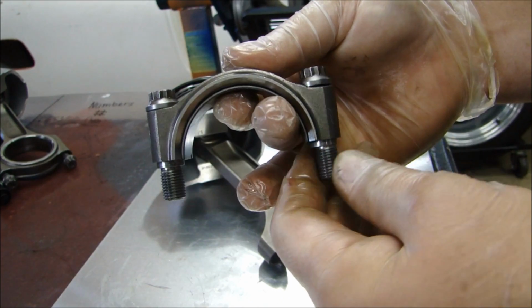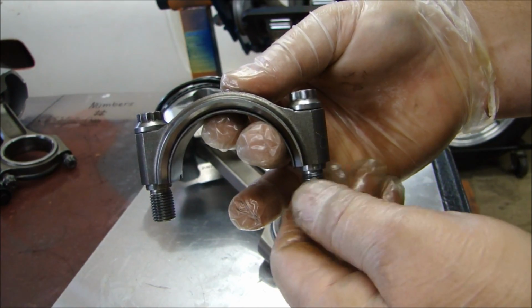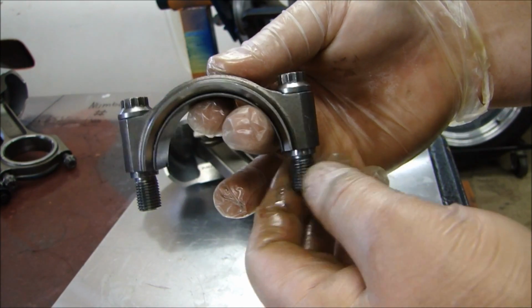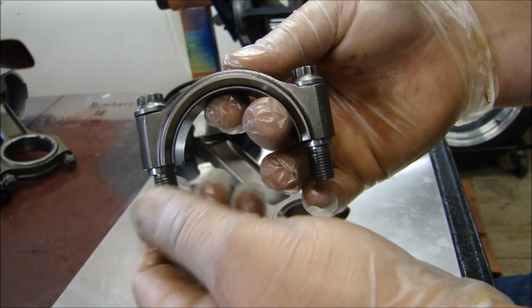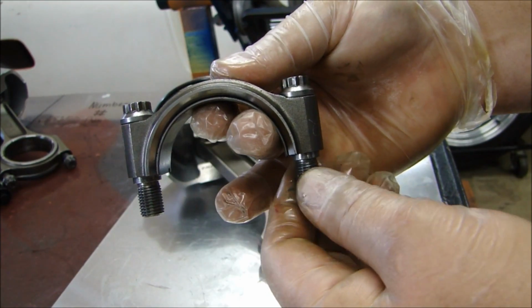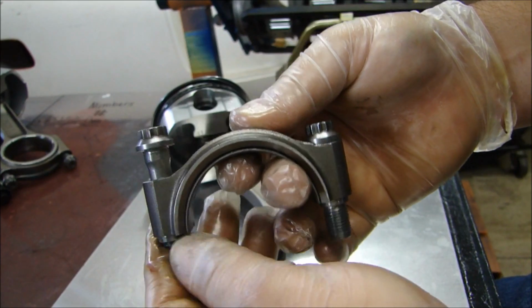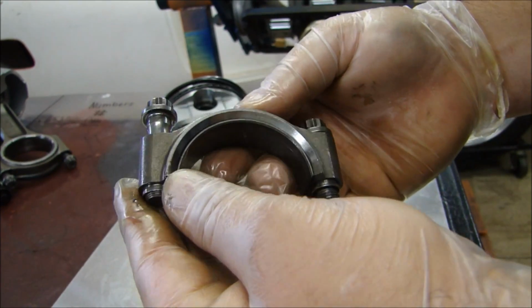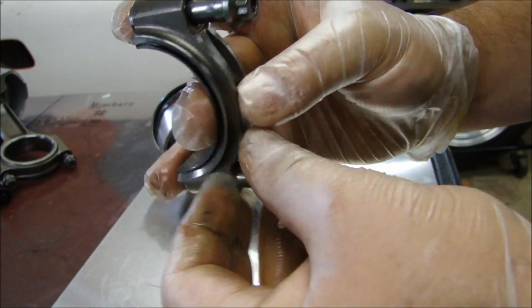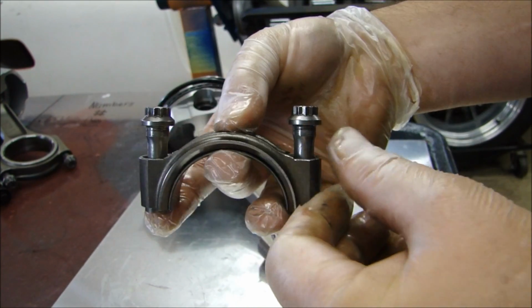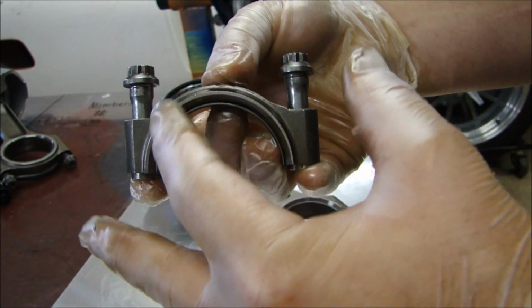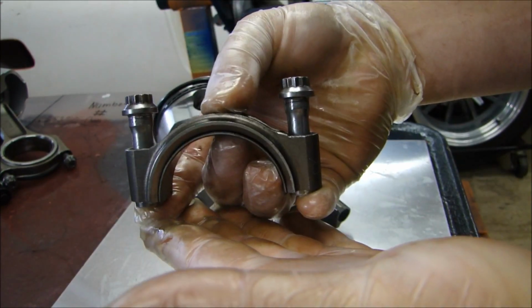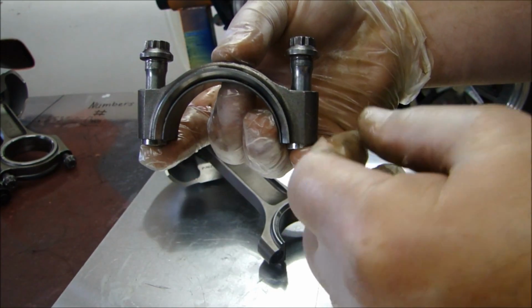But it's because of the heat treatment and the way they do it, and typically a chrome moly is classified as a quench tempered steel, and it can be 180,000 to 210,000 psi for a fastener. And again, recalling that most connecting rod failures are when the bolts fail and the bottom cap falls off the rod as the engine is under the compressive load.